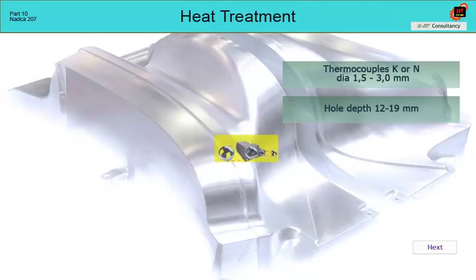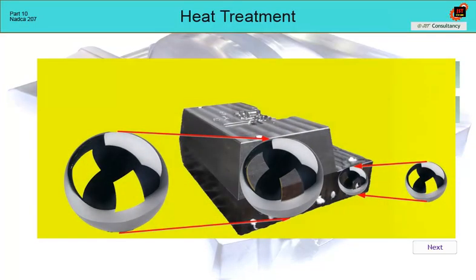NADCA 207, from version 2024, now allows the use of an auxiliary steel block for measuring the temperature TC if we have no other option for placing the thermocouple. The size of this body is described as a sphere inserted into the largest cross-section of the insert. The thermocouple TC is placed in this auxiliary body, and it is assumed that it will have approximately the same temperature profile as the mold insert itself.